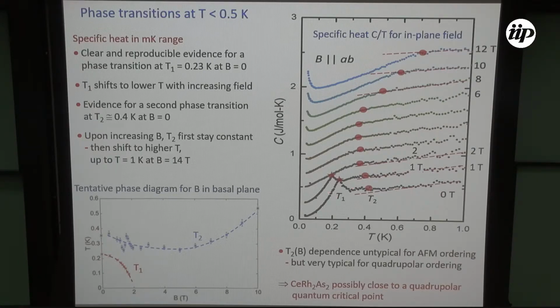And therefore, you have a first very clear anomaly here at about 230 millikelvin at B equals 0. This anomaly shifts to lower temperature with increasing field and disappears at around 2 Tesla. But if you look a little bit more closely, and that has been confirmed by looking at different crystals grown from different batches, you see there's a second anomaly here, which first shifts almost constant, or maybe a little bit down in temperature with increasing field, and then increases in temperature with further increasing magnetic field, and merges exactly with what we observed at 14 Tesla at 1 Kelvin.